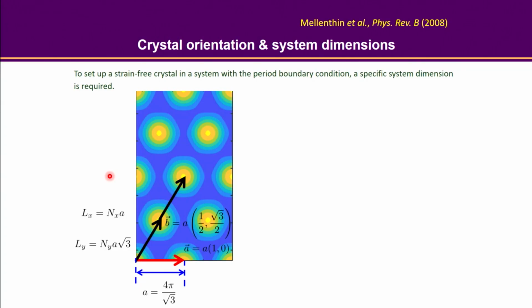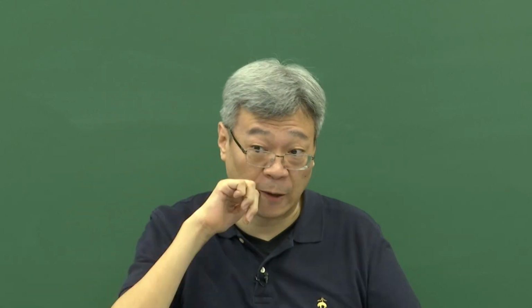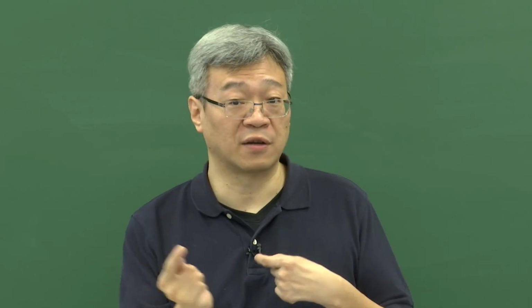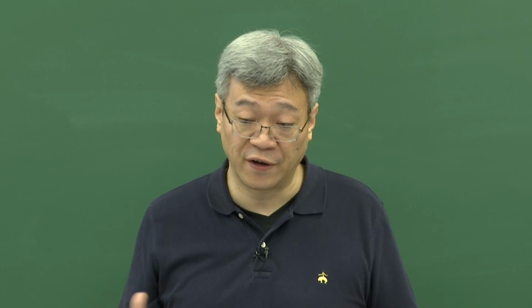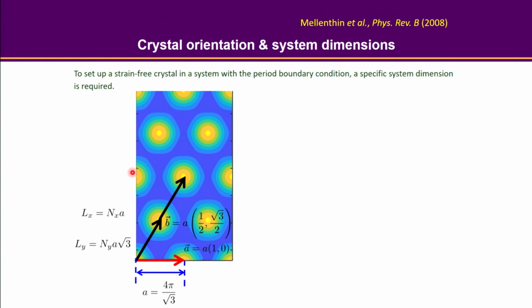In that case, you don't really need to go multiples of cells horizontally. You only need to keep one very simple unit cell, but in the vertical direction you are going to expand your system, maybe 1,000 or 2,000 unit cells. So you really have a very extended dimension, roughly half liquid, half solid. Since along the horizontal direction you have this periodic structure, when you want to get the interfacial energy for this horizontal solid-liquid interface, you don't need a system in the horizontal direction to go beyond this length, because it's already started to repeat itself.